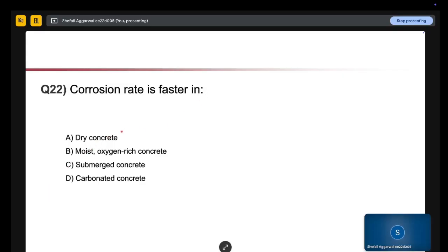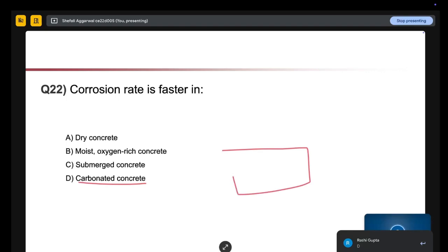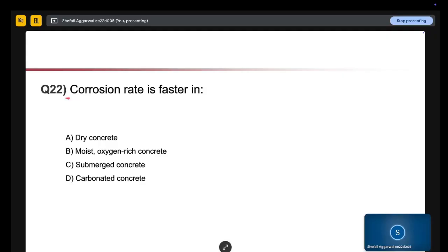Corrosion rate is faster in dry concrete, moist oxygen-rich concrete, submerged concrete, or carbonated concrete. Rate of corrosion we are talking about only. In carbonated concrete, once this much layer, let's say, is carbonated, it will be much denser, which will reduce the penetration of further ions towards the steel bar, so it won't be faster in this case. So mostly the corrosion rate is faster when you have enough moisture and oxygen present on the steel surface. Okay.